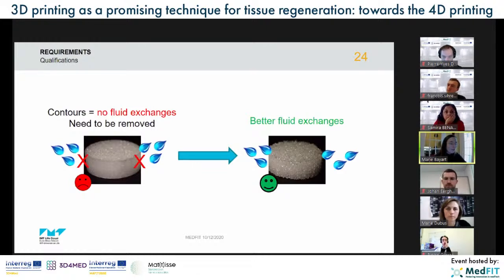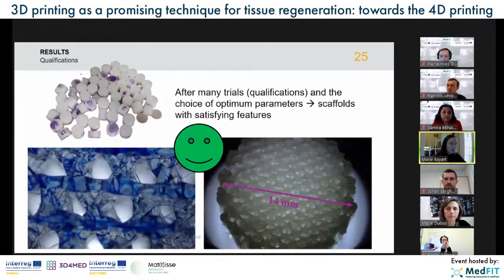Also, the first time we printed with contours, and we noticed that there were no fluid exchanges, so we needed to remove the contours, and it enabled better fluid exchanges in the end. After many trials that we call here a qualification, we obtained optimum parameters, and the scaffold had very satisfying features. Here you can see that we have nice open porosities, interconnection. The pore shape is fine too. The rods are straight. So we were very satisfied with this result.